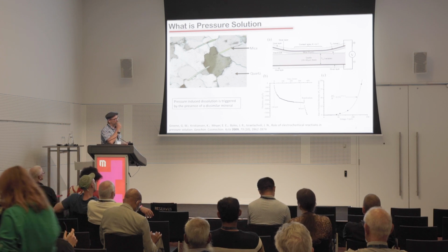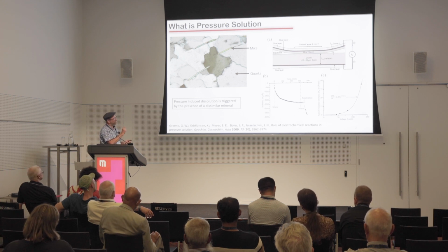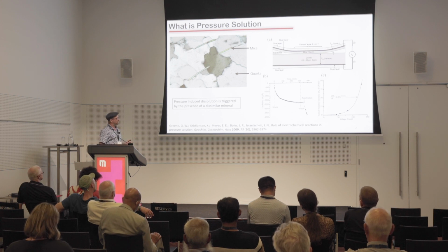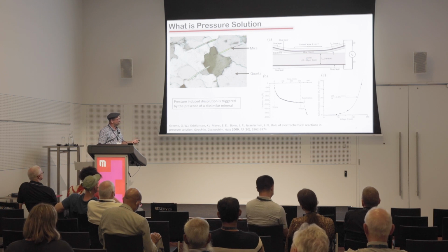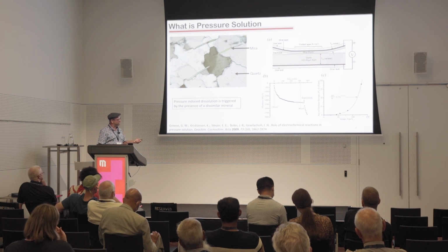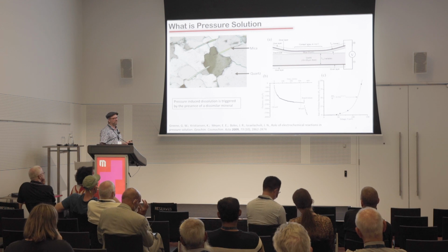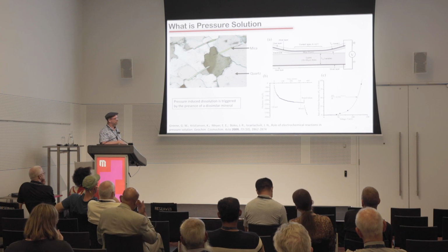Now, a breakthrough came when on a whim, so first of all, what happens if you take a piece of mica and you press it up against quartz? Well, believe it or not, as soon as you press the mica down the quartz starts to dissolve, and essentially the dissolution rate will sort of decay, and then you get these spontaneous reactivation events. And so long as you maintain pressure, it will just continue to dissolve fast and slow, essentially forever.